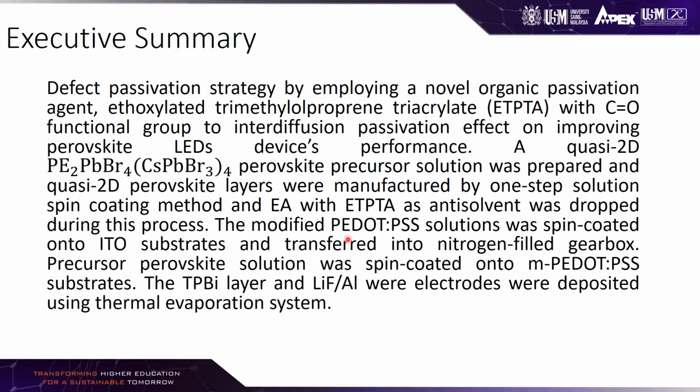The modified PEDOT:PSS solution was spin coated onto ITO, which is indium tin oxide substrate, and transferred into a nitrogen filled glovebox. Precursor perovskite solution was spin coated onto the modified PEDOT:PSS, which we can simplify as MPEDOT:PSS substrate. The TPBi layer and LiF/Al electrode were deposited using a thermal evaporation system.